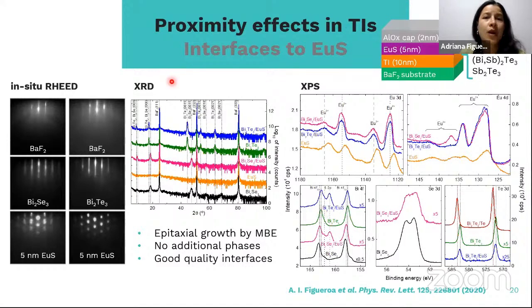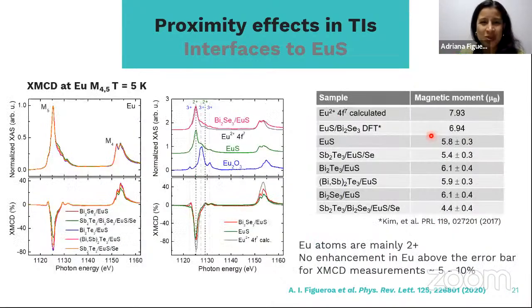So for that, we grew our stacks. We grew topological insulators of this family, with a series of samples of bismuth selenide, bismuth telluride, bismuth antimony telluride, and antimony telluride. We characterized them in situ and ex situ with a series of characterization techniques to demonstrate that there was epitaxial growth with no additional phases, and with good quality of the interfaces between the TI and the europium sulfide. And then we took these samples to the synchrotron and measured XMCD.